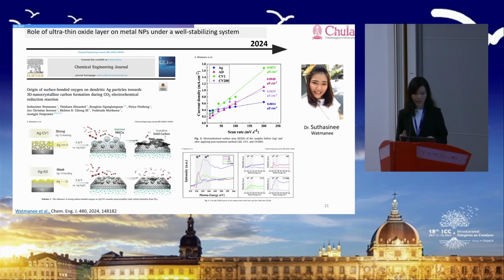Okay, there's something to do with the oxide, so we have to investigate further how much oxide we need, or is there any point where we can even improve further? So we treat this silver nanoparticle. We do electrodeposition first on the copper, and then do some treatment. There are some cases where we can enhance this carbon production, and there's also some cases where we shift the reaction towards CO gas instead of making carbon. So now we actually learn more about that.